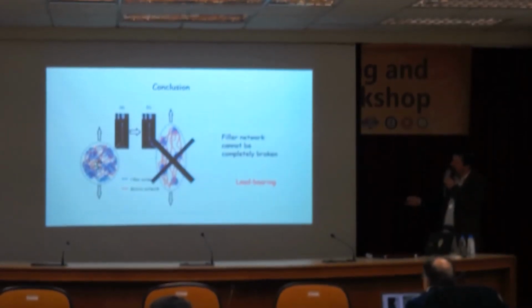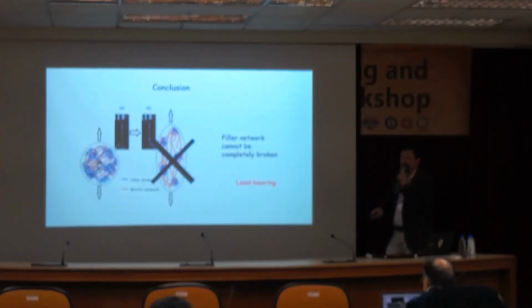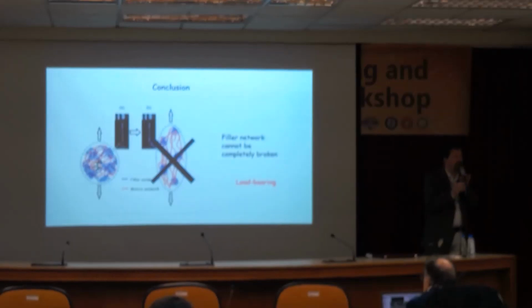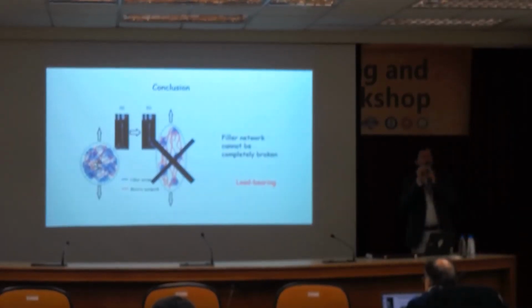In reality, you transfer from the stiff, unbroken, and the soft to something that is a mixture. And this mixture really depends on the initial design. So it's a bit more complicated. You can't just mix soft and hard together and just have a linear combination of the two. The final result really depends on how you break. So right now we are really looking in more detail how this particular blue network is broken, what triggers it, and how do you go from random bond breakage to correlated bond breakage.